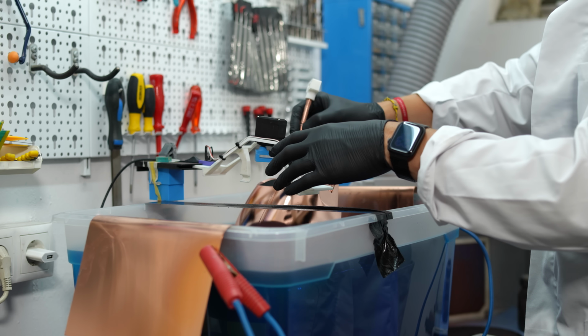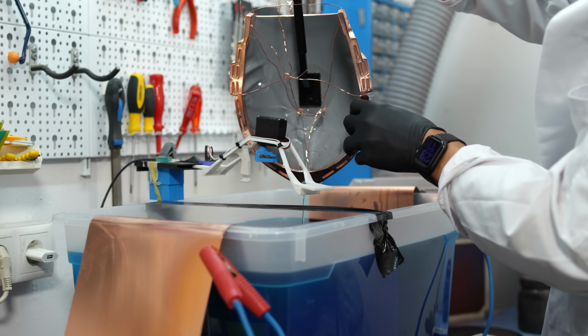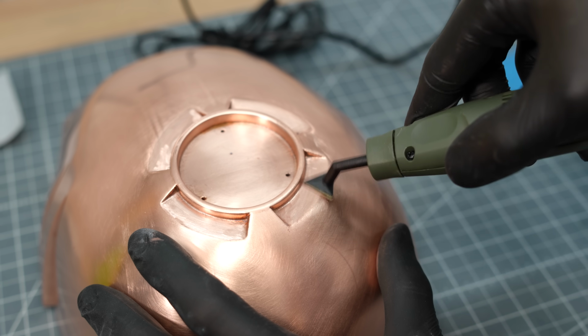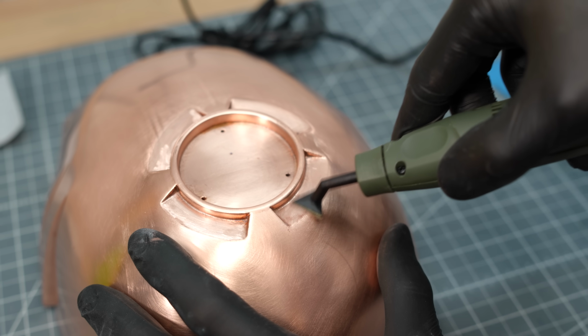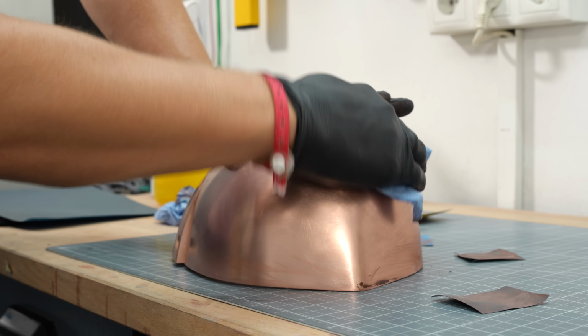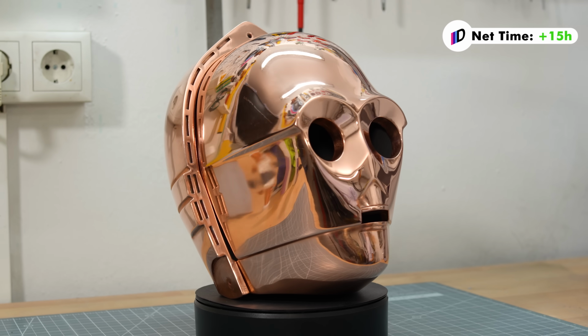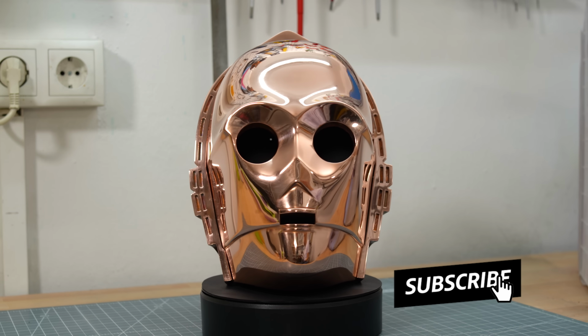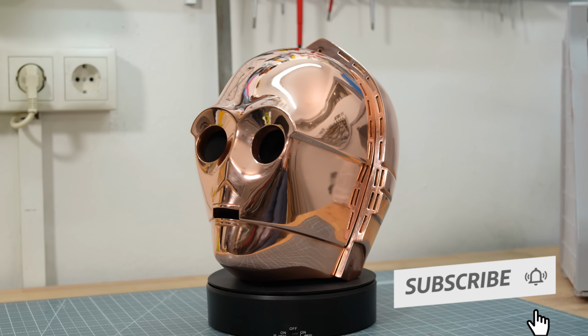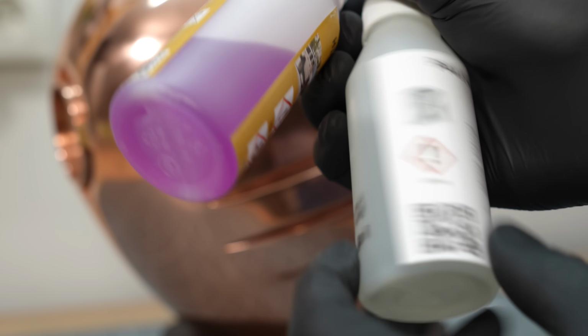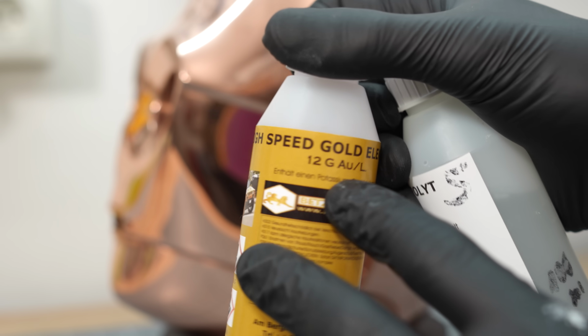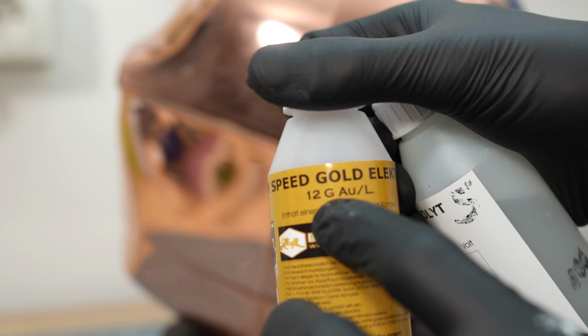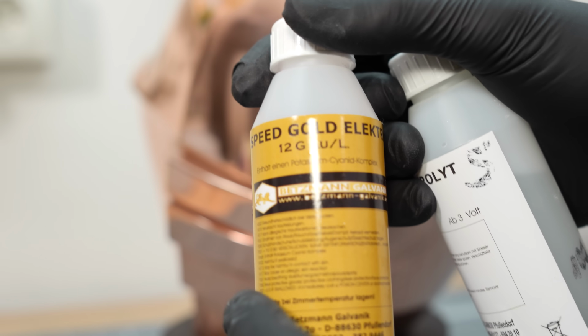For more complex parts, like the rear headpiece here, small sanding machines can be very helpful. In any case, the whole piece now needs to be polished to a high shine. The shine in electroplating always comes from the surface underneath. Next, we use additional electrolytes like palladium and then gold to gild the print. Palladium acts as a barrier layer between the gold and copper.